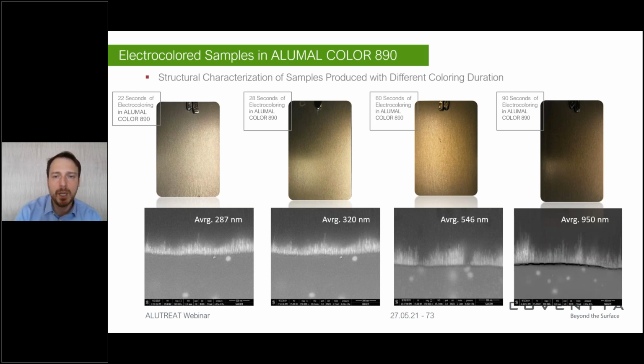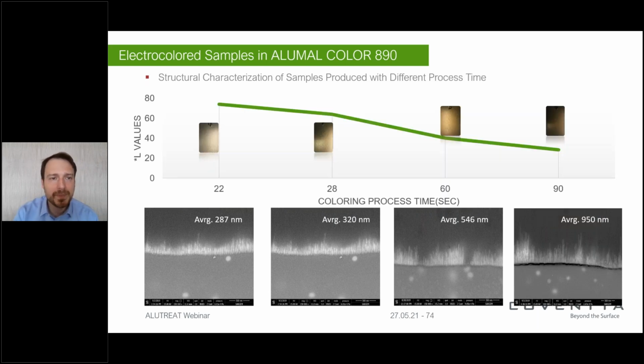So what happens is we were talking about 8 micron of precipitation for dark bronze or 15 micron. We are talking here about nanometers, and they're affected by almost everything. Hence, you can see that even a small change, about 6 seconds or 10 seconds, changes the L value from 70 to 40. So that's a huge change. Therefore, you need to be very careful about how this process is going on, let alone making the same color on the same parts.